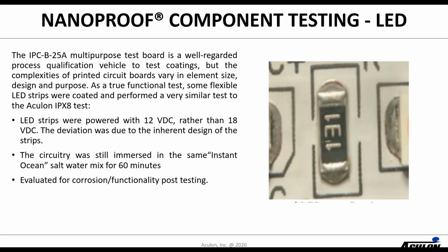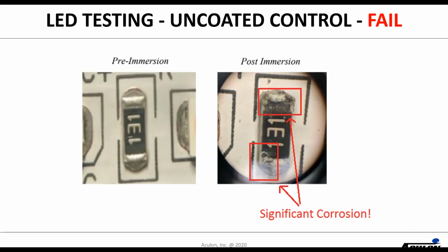So that meant we had to move on to a different test that would show a real world example. And in the real world, your components are not flat. They have multiple components, multiple chips of 3 dimensions. And when the coatings are put down on them, what will happen is the coating slumps. And so the flat areas will be protected, but the edges and the corners and exposed areas will fail. So you might have a thick enough protective layer to protect a flat area, but if the corner is exposed, you're going to see failures.